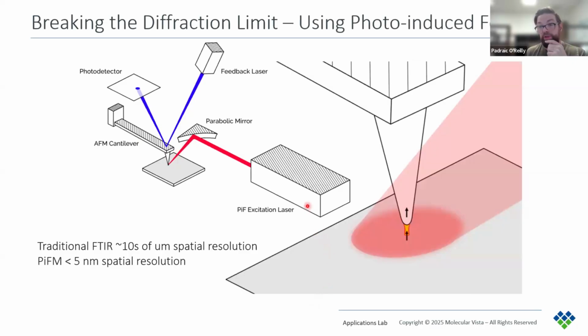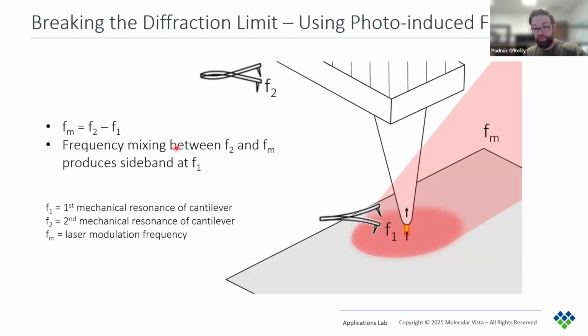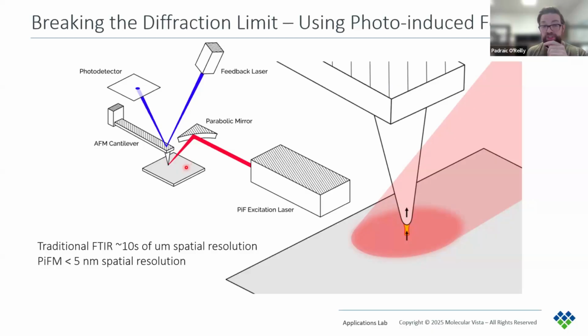So to break this limit, we couple an IR laser with an AFM. So for those not familiar with AFM, fundamentally you have a cantilever, with a sharp tip, which is scanned across a surface and detects changes in the topography. Now, in this cartoon, you see that we also focus this, what we call the PIF excitation laser, at the tip sample interface via a parabolic mirror. And so in terms of this presentation, this laser will be an IR laser, and the power at the surface will be somewhere between 100 to 1000 microwatts, which will not damage your sample. It won't be strong enough to do that. And the upshot of this is that we take the spatial resolution of IR from 10 microns or so to